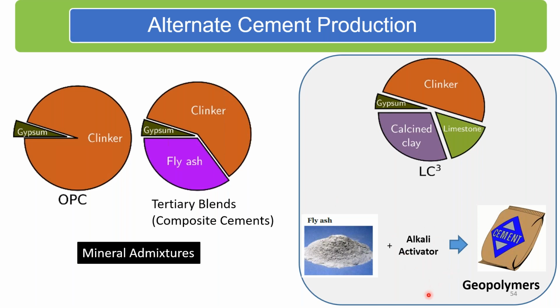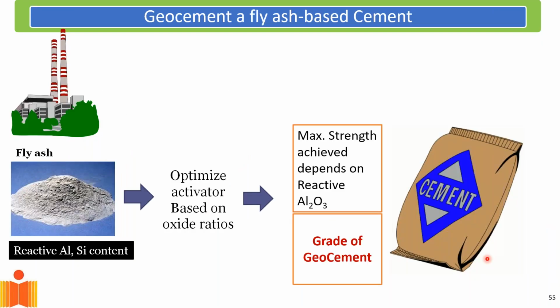And here we have this whole group of cements binders that we call alkali activated binders, where you start with a waste material, which is a source of silica or alumina, such as fly ash, activated using alkalis, and then we are able to produce cements. One class of cements is called geopolymers. The other cements are typically called alkali activated slag based cements.